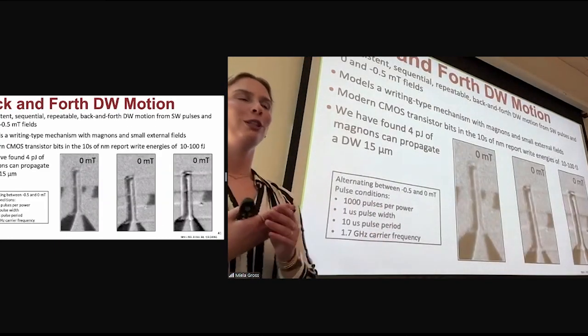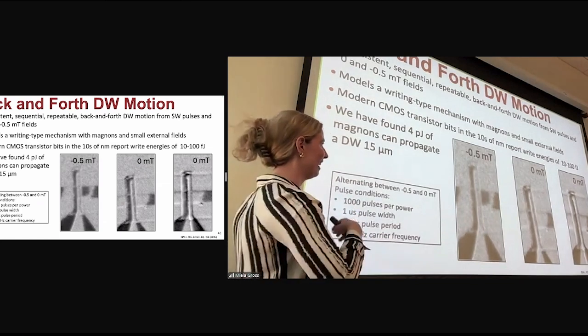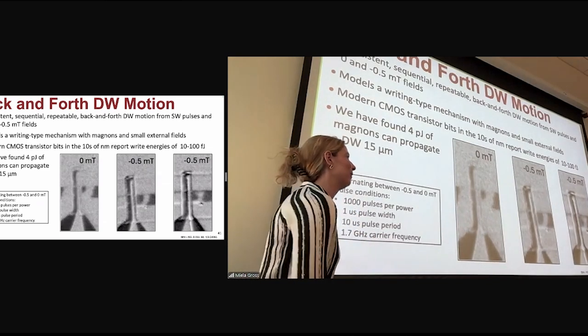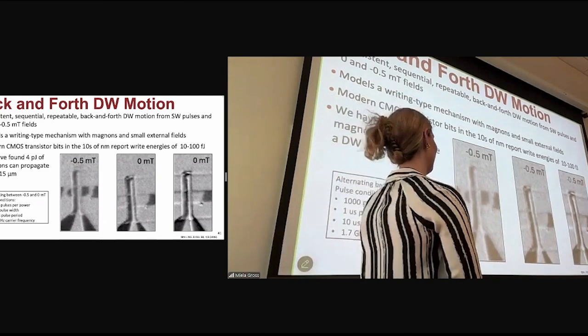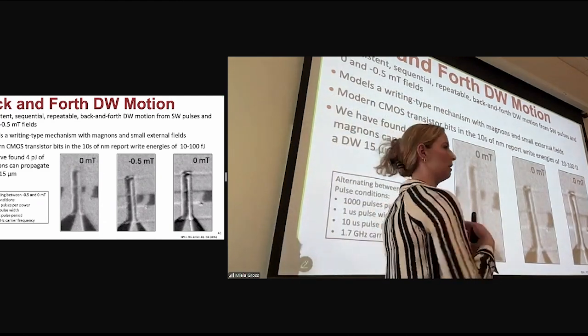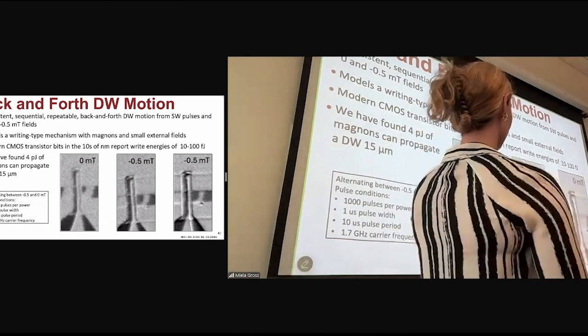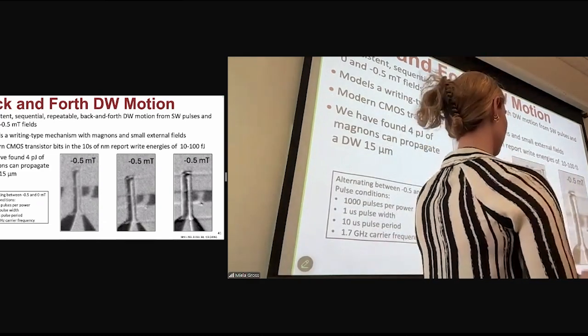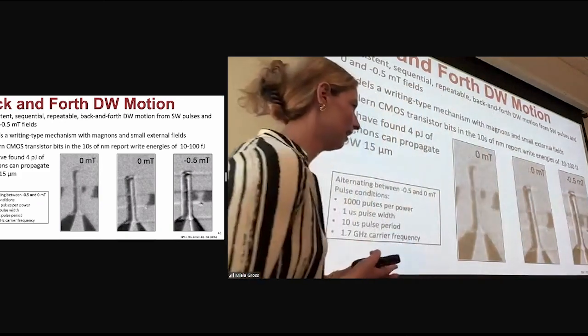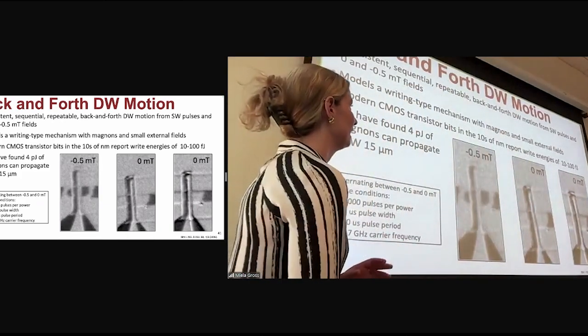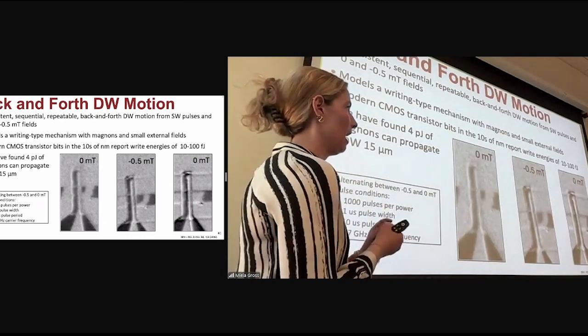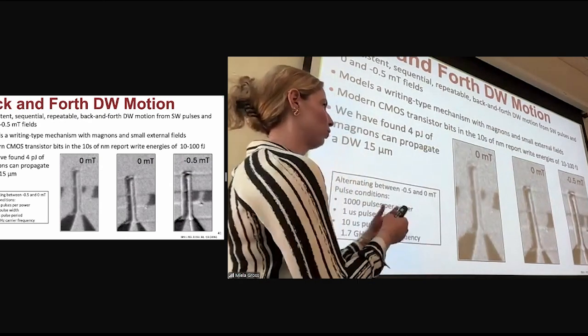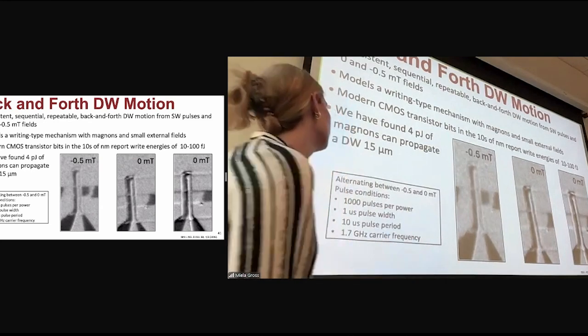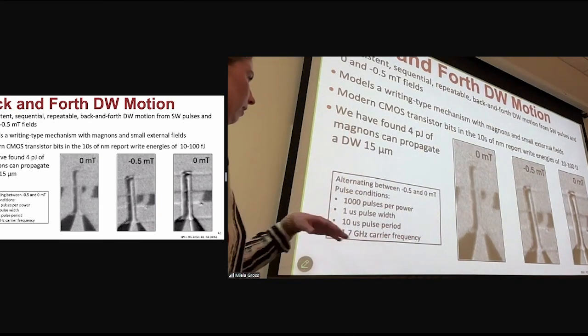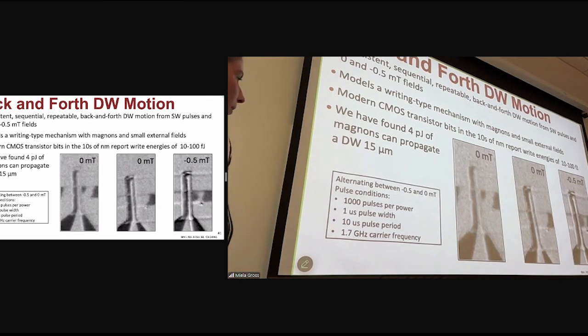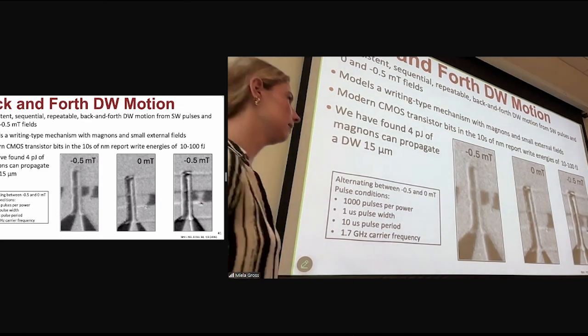So I would love to use the knowledge that I gained with the past couple slides to try to create this back and forth motion. So that's what this slide is all about. It's showing back and forth motion of these domain walls with small external fields and very short spin wave pulses. And so this, I thought, is a great model for a writing type mechanism with just, again, these really small external fields and short RF pulses. So the pulse conditions for the movies you see on the right here are listed here. Specifically, we used 1 microsecond pulse widths with these devices.